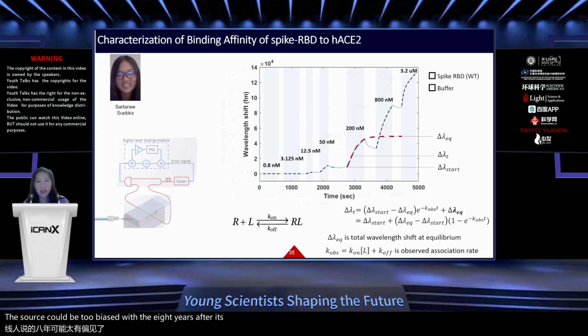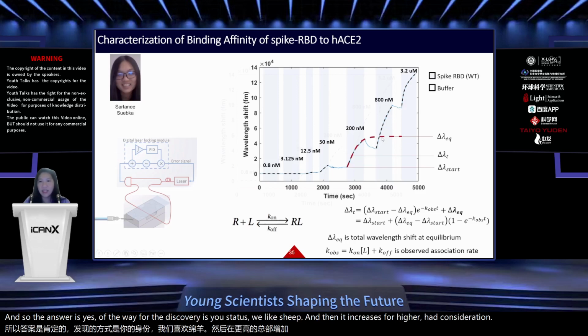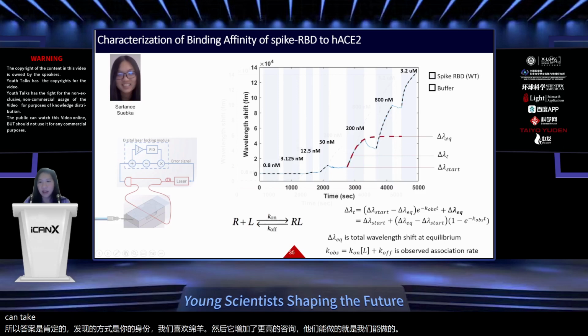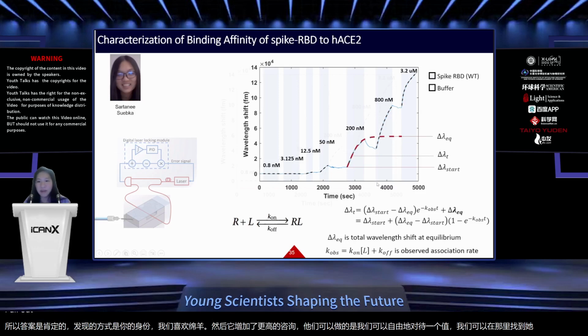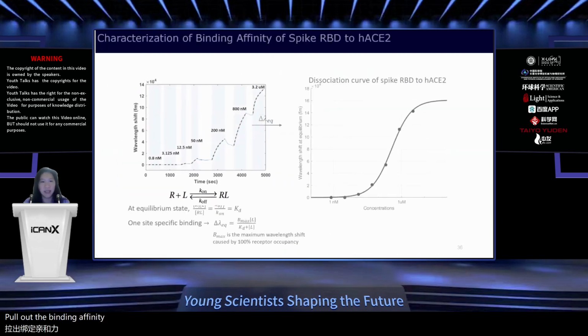in your lung. So the first thing that we did was, can we get accurate binding affinities with our sensor? And so the answer is yes. So the way you interpret this graph is you see this wavelength shift, and then it increases for higher and higher concentrations. And then what we can do is we can take the equilibrium wavelength value, we can get a binding curve, and from there we can pull out the binding affinity of various things.